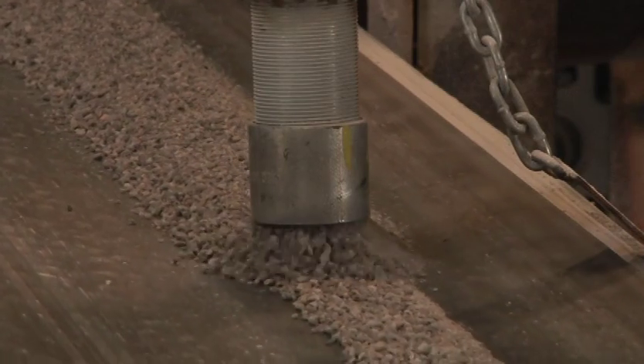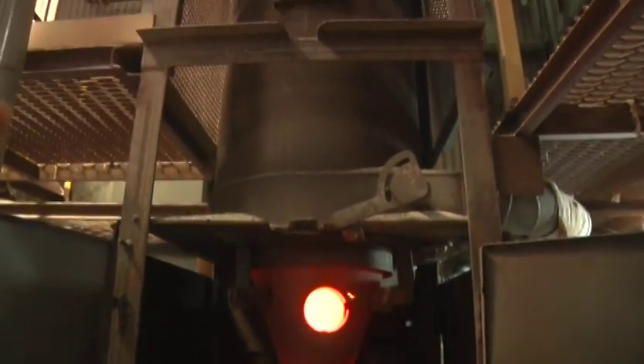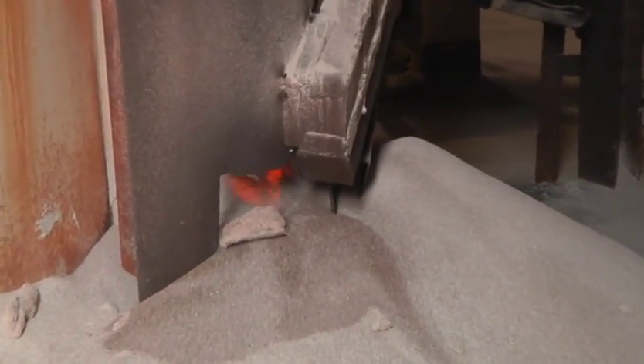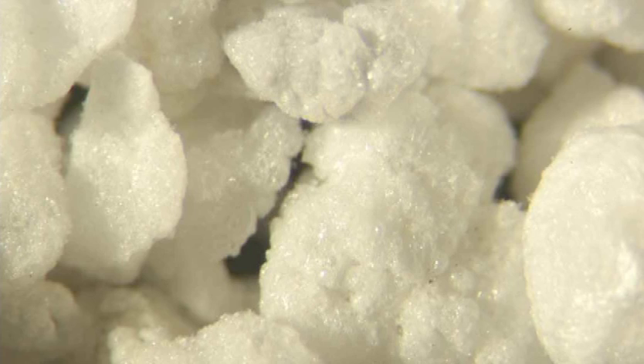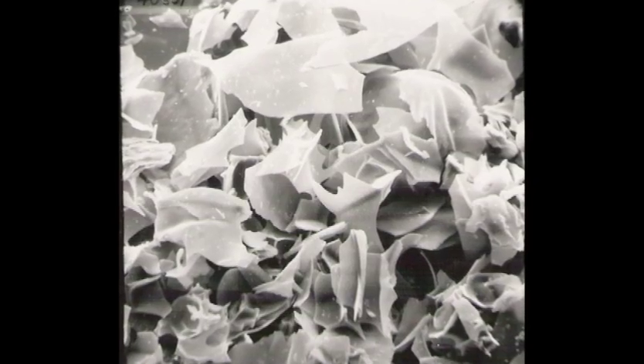The secret that turns perlite ore into something special is heat — and plenty of it. When the gray perlite ore is heated to about 1500 degrees Fahrenheit, the glass softens and the water molecules inside turn to steam, and the ore pops up just like popcorn. Each small piece of ore grows 12 to 15 times its original volume and, under a microscope, looks like a cluster of tiny glass bubbles, both whole and broken.